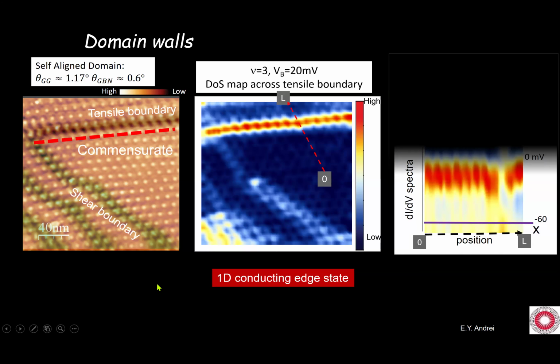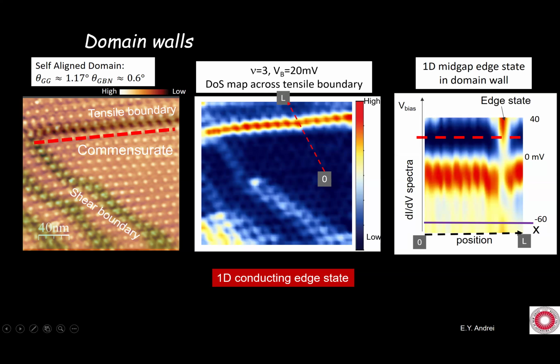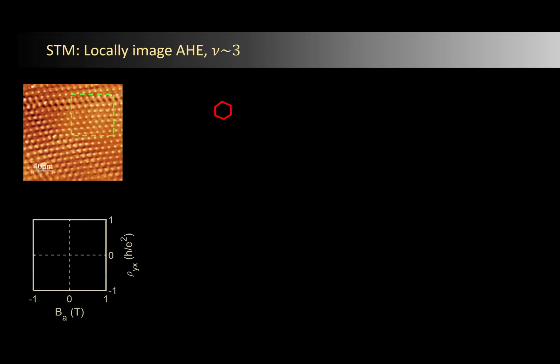Now, if I'm looking at the dI/dV spectra as a function of position, I'm going along this line. I'm here, so you see nothing, I'm in the gap, and now I'm hitting the edge state, I'm getting a large density of state here. So are these the chiral edge states that we are all after and that give rise to the anomalous quantum Hall effect? And then we kind of repeated the experiments that the transport people have done.